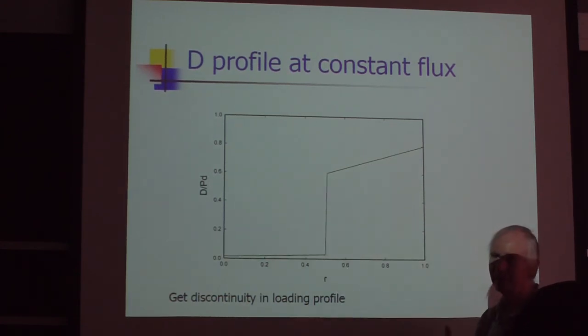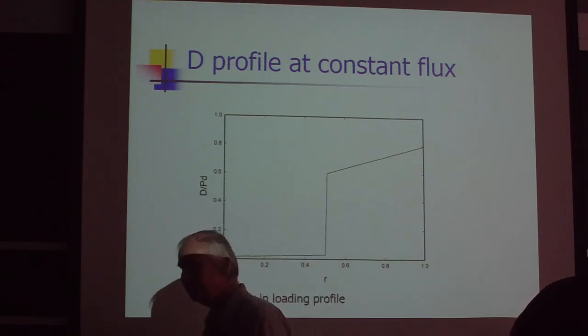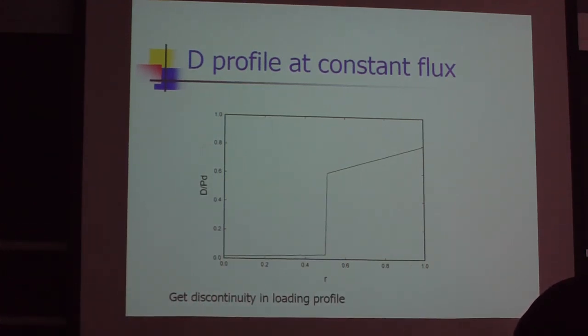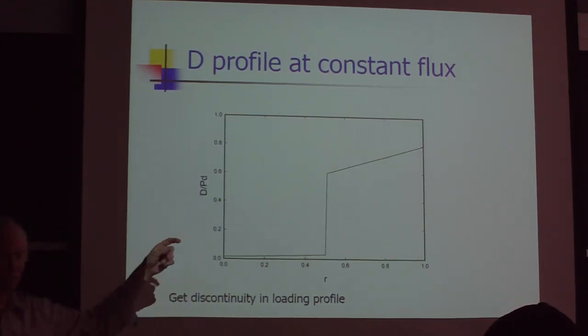And so you would expect this to have a possibility of doing a lot of damage to your local crystal structure. People have done measurements—I have some papers with x-ray measurements from the 1930s, where they would load. They start with a perfect crystal of palladium. They load the hydrogen, measure x-ray measurements to look at grain size. Before loading, very large grain size, and by the time they were done, no grain larger than a micron. Basically micron scale.